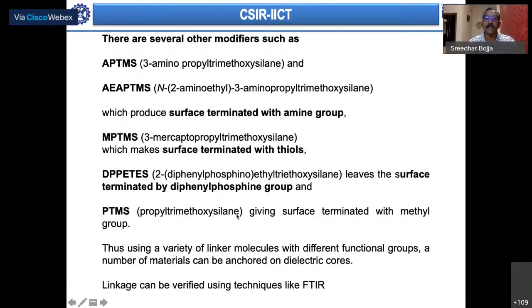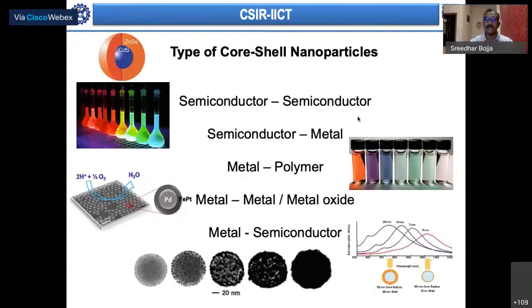But once you have synthesized these materials, you have to characterize them. For that, people normally use FTIR, because once you have these functional groups, the functional groups that are on the modifiers can be easily detected by FTIR. You can say that yes, this surface is modified with this kind of material, and this material has these functional groups which are identified by FTIR. So we try to work on those kinds of things and try to understand.